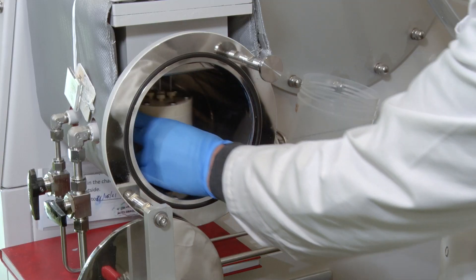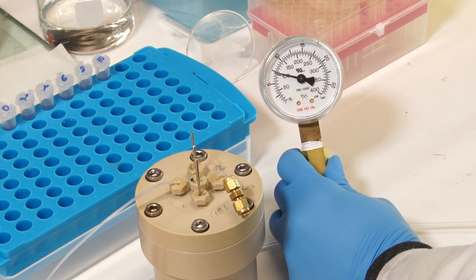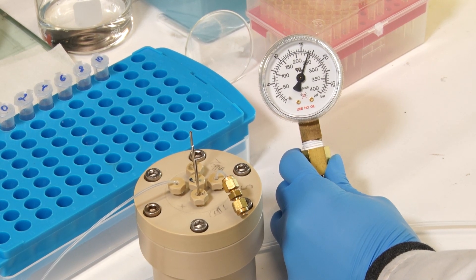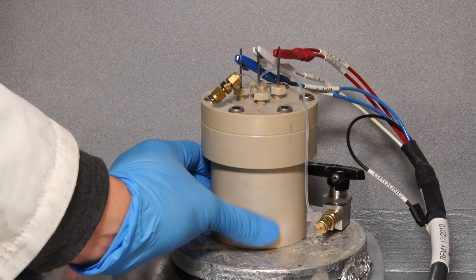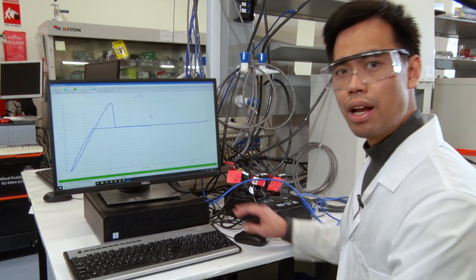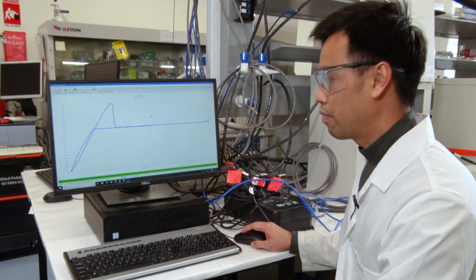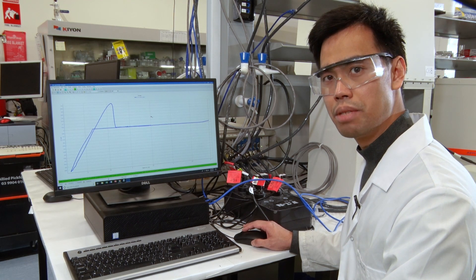And then we bring it outside the glove box. Introduce the nitrogen gas at as much as 20 atmospheres of pressure. So we will start an experiment. We will run this for three days. Afterwards, it is time to measure how much ammonia has been formed.